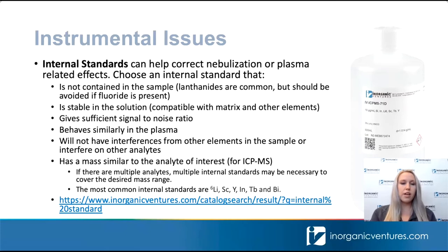You also want to make sure that the internal standard is going to give a sufficient signal-to-noise ratio at the concentration that you're spiking it into the solution at, because you want to make sure that you're getting accurate results for that internal standard so that you can apply that to your analytes. You also want to make sure that the standard is going to behave similarly in the instrument in your plasma as the analytes, because if you're seeing an effect on the internal standard, you want to be sure that it is going to have the same effect on your analytes.